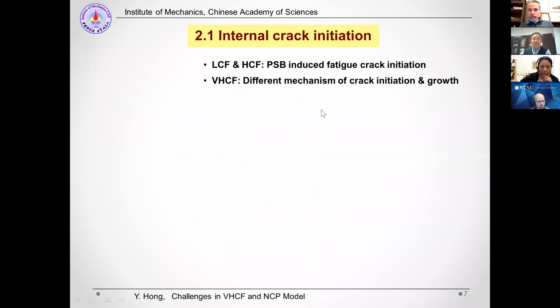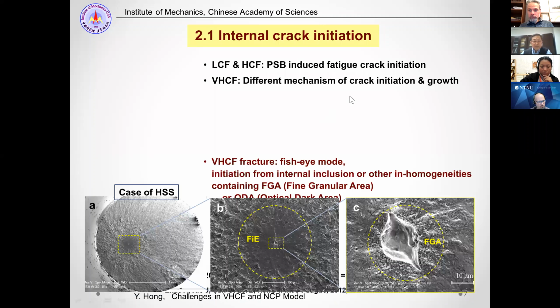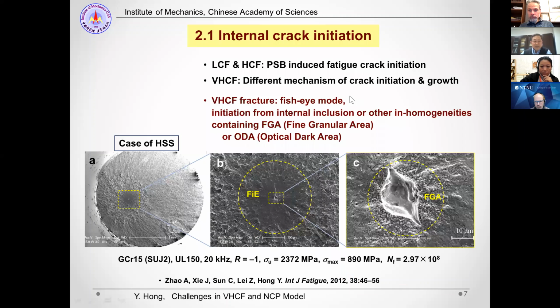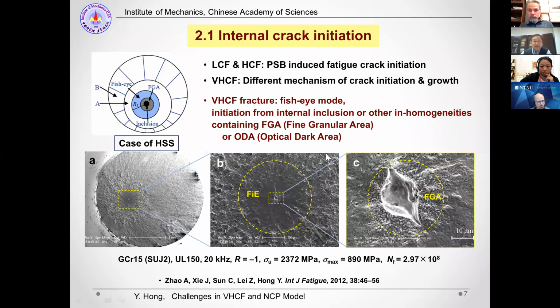And the first point, internal crack initiation. We all know that the fatigue crack initiation in low cycle and high cycle fatigue is due to persistent slip bands. But in very high cycle fatigue, the crack initiation and growth mechanism is different. Normally, the crack is always initiated in the interior of the specimen, like this morphology, and also showing a kind of fisheye feature containing a rough area called FGA, fine granular area. So for high strength steel, this schematic showing this process, crack initiation from an inclusion and a rough area, and next fisheye region, and then final fracture.